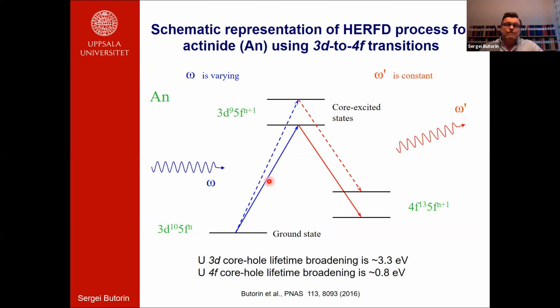So by scanning the incident energy and counting all the photons or electrons outgoing from the sample, regardless of their energy, we will measure a conventional X-ray absorption spectrum, which will be broadened by the 3d core-hole lifetime. But these core-excited states can decay into states with a 4f core hole.